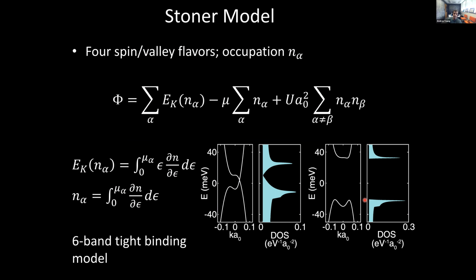It turns out you can understand this very simply by taking a Stoner model. What a Stoner model basically does is it says there's some energy that you get from just filling bands. So that's this first term. The second term is basically saying there's an overall chemical potential, so this is all a grand potential in terms of this chemical potential. The alphas are densities of different flavors. And then you just add a pretty much phenomenological exchange term that favors filling the same flavors. So it's not a microscopic calculation.